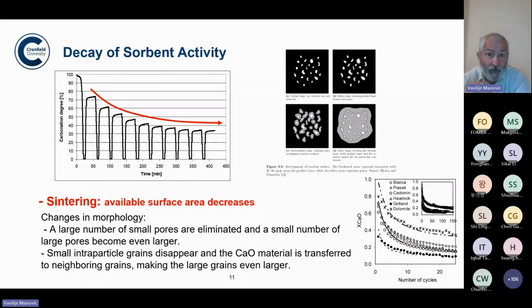The solution was to always make up fresh material and to purge a portion of material from the process. But it's increasing the cost of the process, especially in scenarios where we have no market to use that spent sorbent that we purge from the system. For example, in the case of power generation, we usually don't have the opportunity to use spent sorbent for something, and we need to think about other solutions. We were thinking about how to reactivate that material. And usually we consider that sintering is happening in the material, which means decreasing pore surface area and decreasing pore volume of solid particles, and that's the reason for lower activity with each cycle.